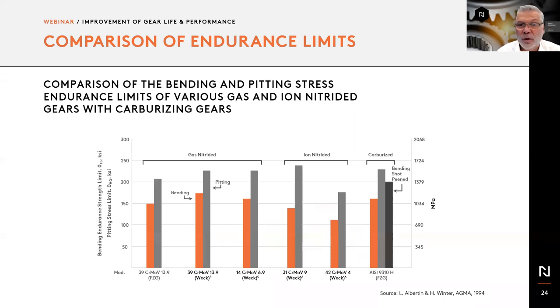And it goes back to, again, the compressive stress level that we have been talking about before. We read very often compressive stress as hardness when you look at the curves. However, it is compressive stress, and it is somewhat best illustrated by the last column to your right, when you see a carburized component that has been shot peened. Shot peening is often used in many applications, one of them being valve springs, for instance, in automotive applications. But shot peening does produce compressive stress on the surface. And this compressive stress performed on a carburized component improves resistance to bending and provides a better bending fatigue resistance. So it's a more enduring part, and it illustrates why nitriding, naturally providing this compressive stress, withstands better some of the applications.